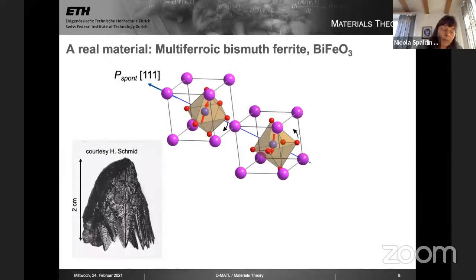Here's a rather beautiful crystal from Hans Schmid's collection. You see it's rather large, a 2 centimeter across crystal of bismuth ferrite. It's very attractive. These fern-shaped textures are because of twinning in the crystal. So it's a really beautiful piece of crystal, but it's of course not very good for doing ferroelectric measurements and so on. So with this crystal, it was not established that bismuth ferrite was a good multiferroic.